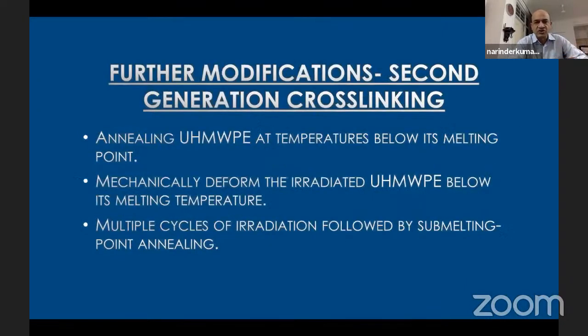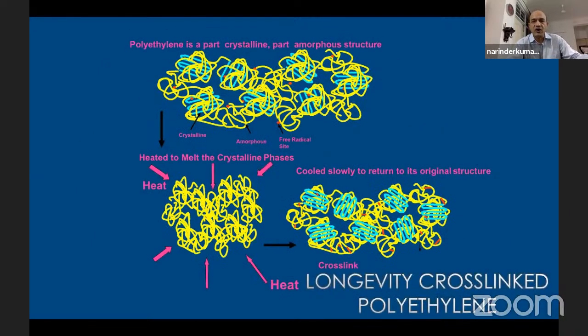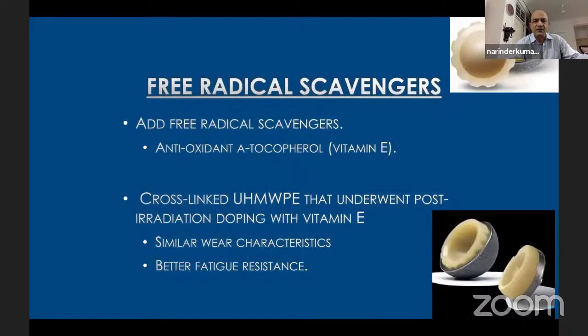The first generation and then second generation cross-linking happened with addition of the annealing process, which is multiple cycles of irradiation followed by sub-melting point annealing. This is how a longevity cross-link poly from Zimmer is manufactured. I won't bother you with the technical details, but finally, during this process, you can add free radical scavengers.